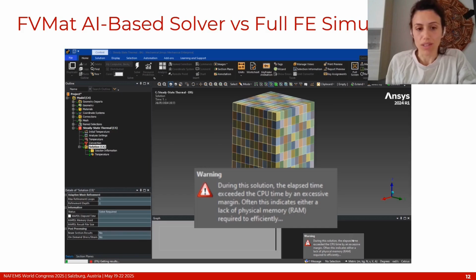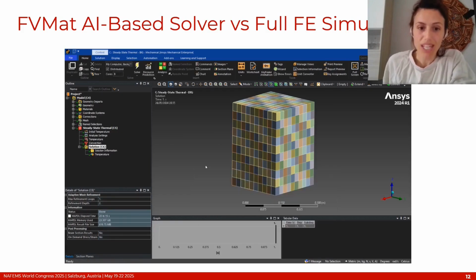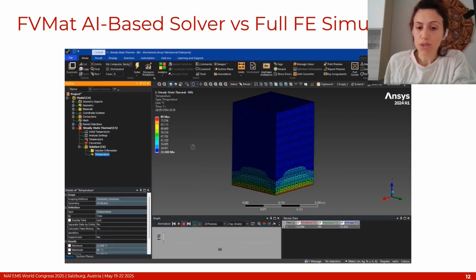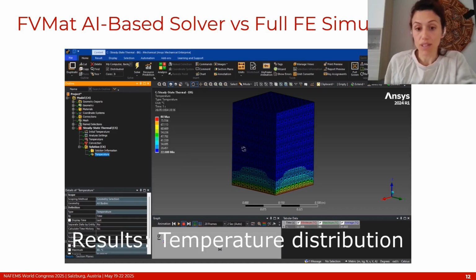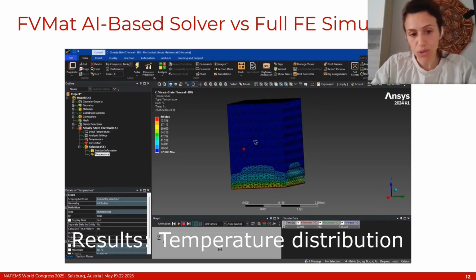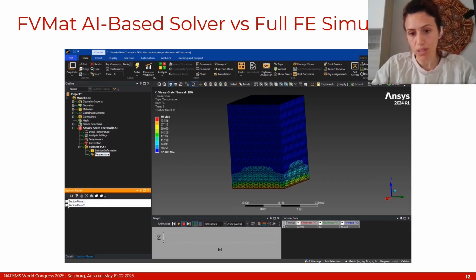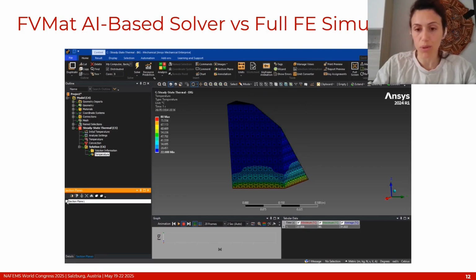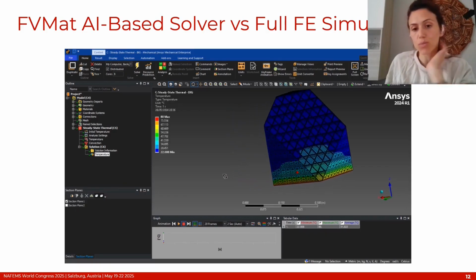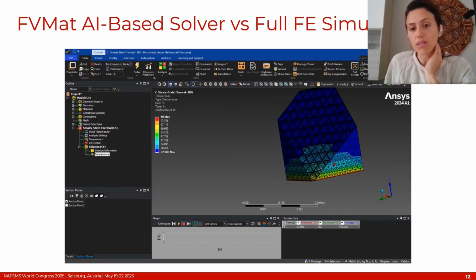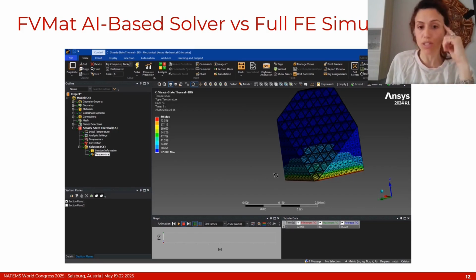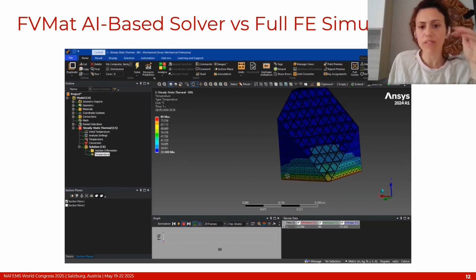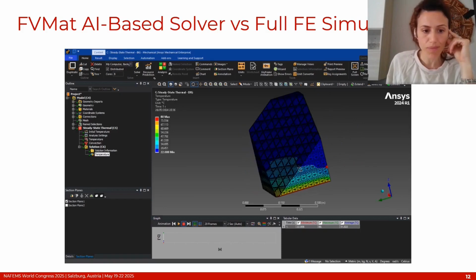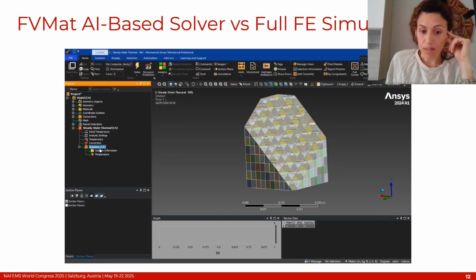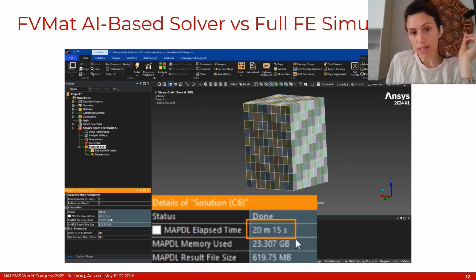There's also a warning that the time was too long. And in the end, we get a temperature profile in this body with a high temperature on the bottom, where the high temperature was imposed as a boundary condition, and a temperature profile going from hotter to colder until the top, with a very specific profile. The total elapsed time was 20 minutes, 15 seconds.